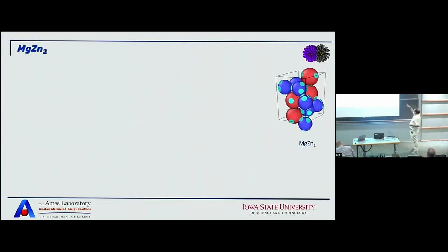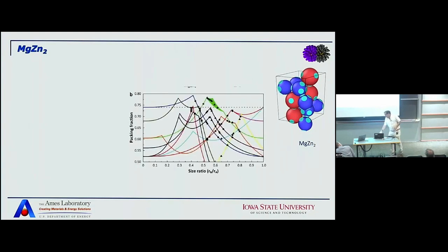If you do that, you will see that this is actually a diamond lattice where the red ones are in touch with each other. And the blue one is actually a pyrochlore lattice, which has coordination 6, and they are also in touch with each other, but they do not really touch the blue and the red. So according to the rules that we have postulated, the reds can be deformed because they have coordination 4, but the blues cannot, because they have coordination 6. Therefore, for magnesium zinc 2, which is the yellow line here, when you take that into account, the right part of the curve corresponds to the blue ones, but the left part is the red ones. And therefore, those are the ones that can be deformed.